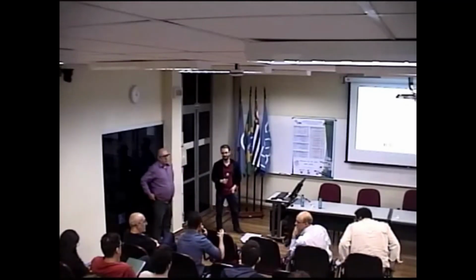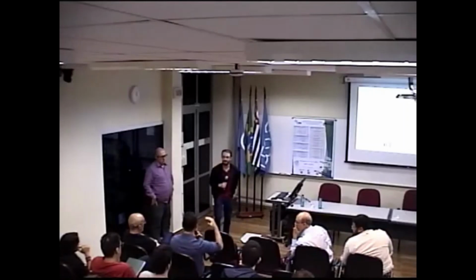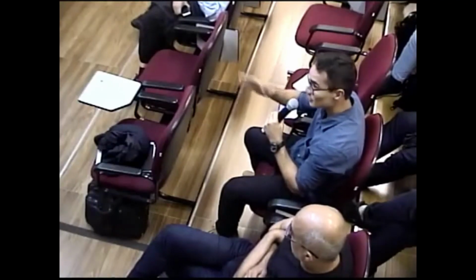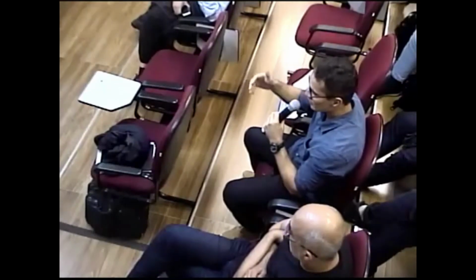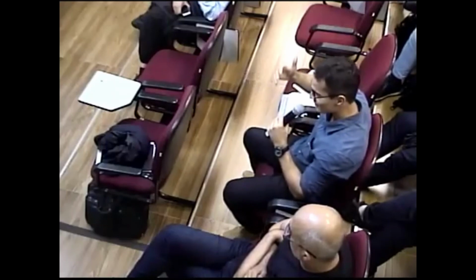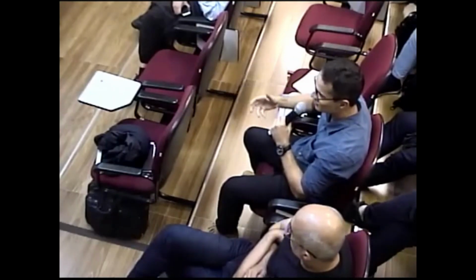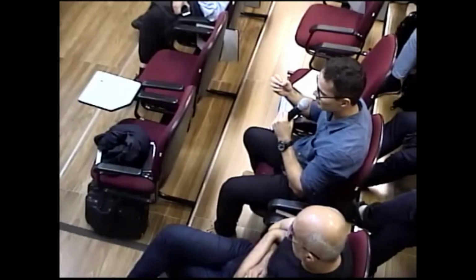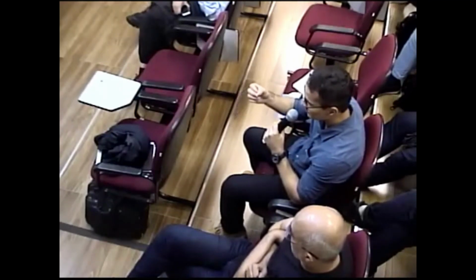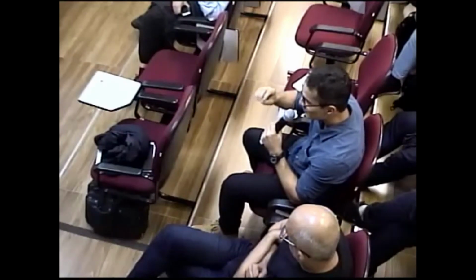So last week, a friend shared with me an article explaining the science behind the Lycurgus cup. It's a piece of art made from glass, and it's very interesting because the light that is reflected is green, but the light that goes through the glass comes out red. So it took us like, I'd say, 1,500 years to develop our modern science, to discover how a craftsman back in the day had the ability to develop a material like this. And they discovered that this very specific aspect of the material is due to the nanoparticles of silver and gold in a very specific concentration and also a very specific size distribution.